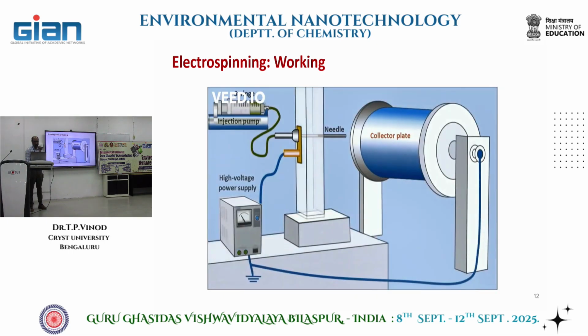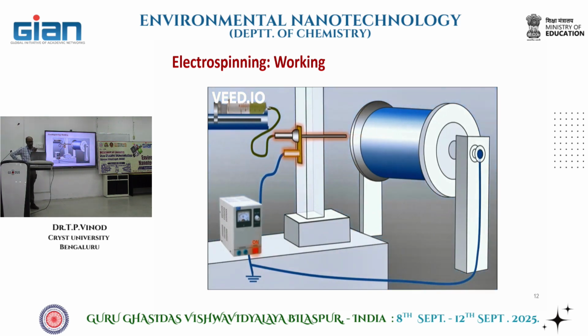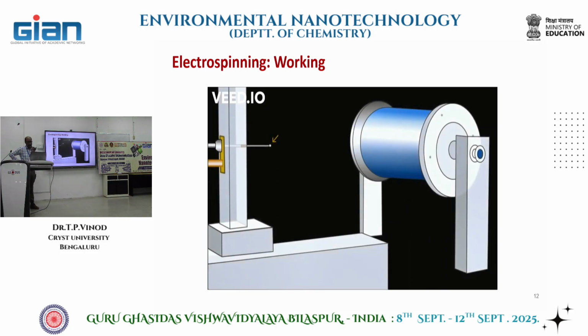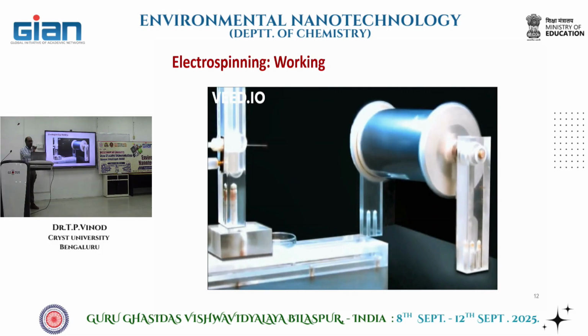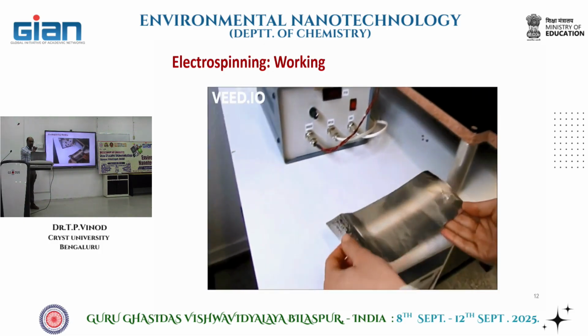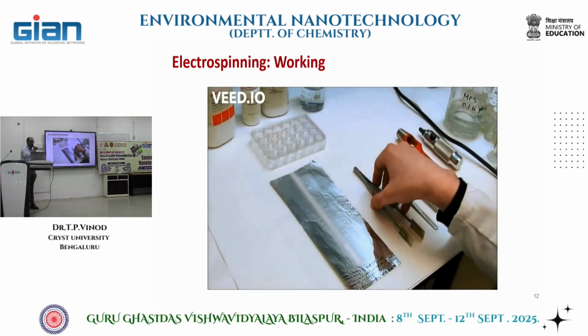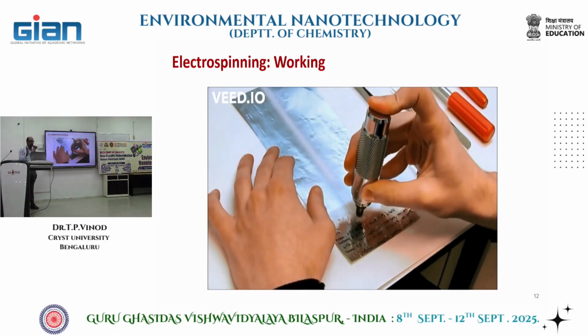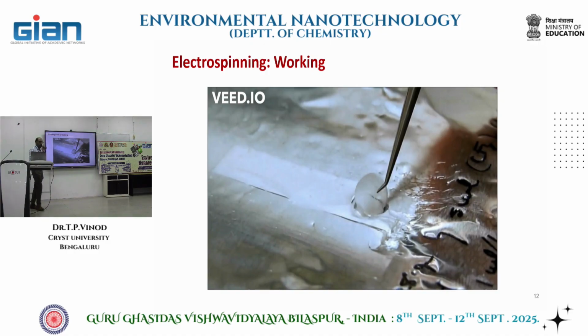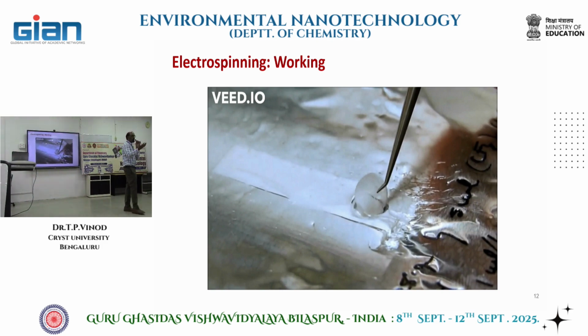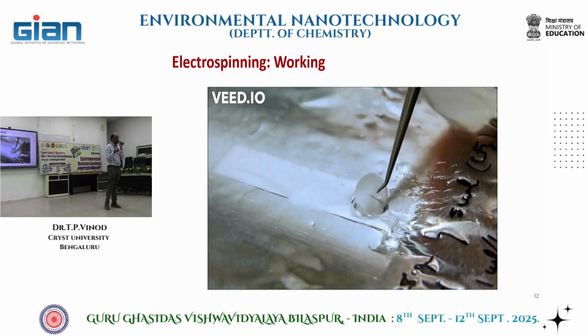So finally, how you get it is like this. One more time, I will play it. Okay, so now it went to a real video. So it's usually on an aluminum foil, and this is actually a very thin film. Usually it's very easily detachable if it is a thick film. And then you can cut it to an appropriate size, and that comes as a freestanding film. The thickness of it actually depends on the deposition time. The more you deposit, the thicker your film will be.